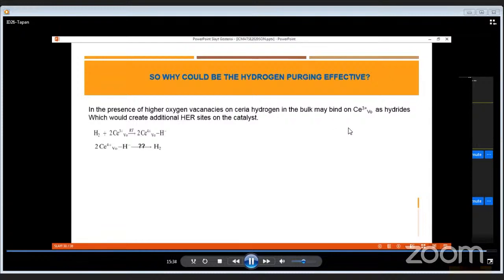During hydrogen purging of reduced ceria, it will cause formation of hydrides by electron donation from oxygen vacancies, and these hydrides could be responsible for high hydrogen evolution rates.